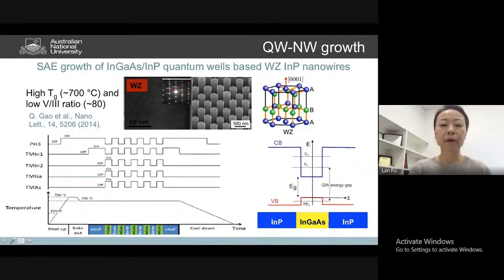And then we keep going, switch off, for instance, the gallium source, and switch back indium, switch back with phosphine. Thereby we can grow indium phosphide. So by switching back and forth different precursors, we're basically able to grow quantum wells with barriers, multiple quantum wells with multiple barriers, such as the example given here, right? InGaAs quantum wells growing here with indium phosphide barriers. And if you look at the bandgap structures, you have InGaAs, you have indium phosphide. That's the simplified bandgap structure for an InGaAs quantum well.